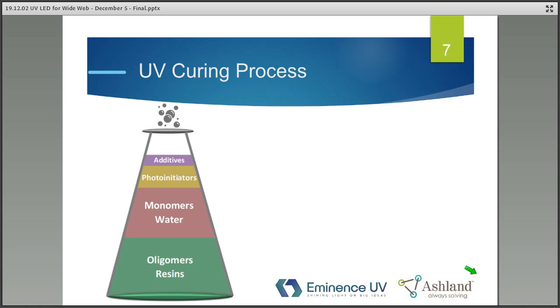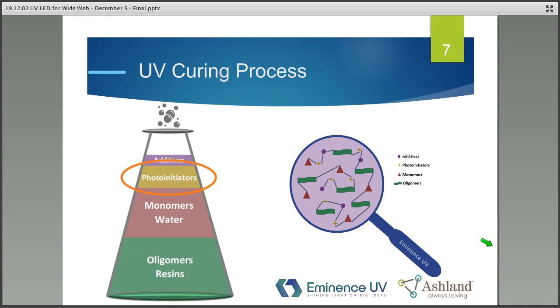As I mentioned earlier, there's no real water-based carrier or solvent carrier that has to be flashed off. It doesn't mean there's not water in the formulation. It just means that it's a much more solid solution. You have oligomers, which form the base of the coating or ink or adhesive, followed by monomers that are going to give you some dilution qualities, photoinitiators, which react to the UV light, and then additives, which give you additional processing control, color, pigmentation, defoaming. The key ingredient, though, is that photoinitiator. Without the photoinitiator, the ink coating or adhesive would not react to the light.